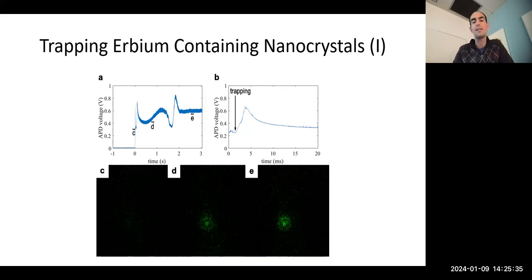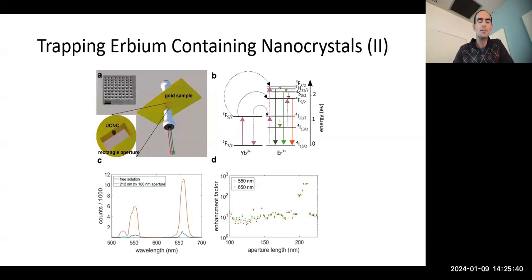So when you trap them, you see clearly this green emission, telling you that we've trapped them, even though we use an infrared source. Once we trap them, we try to do Purcell enhancement, enhancing the optical emission from these emitters. Our strategy was to look at different size apertures, tuning the aperture size to match the resonance with the emission or excitation wavelength, thereby achieving more photons out of these emitters. We were successful in doing this.